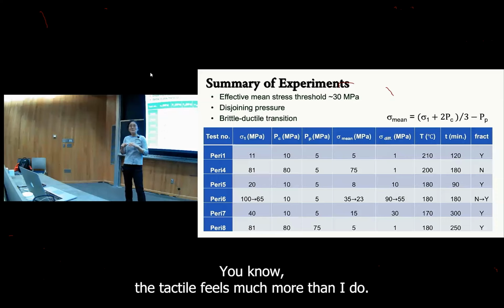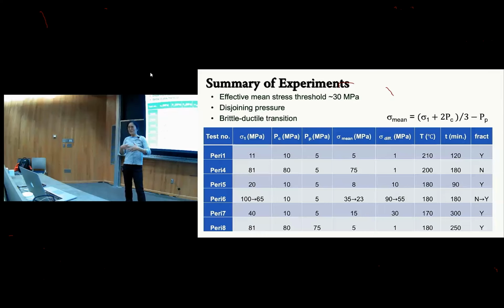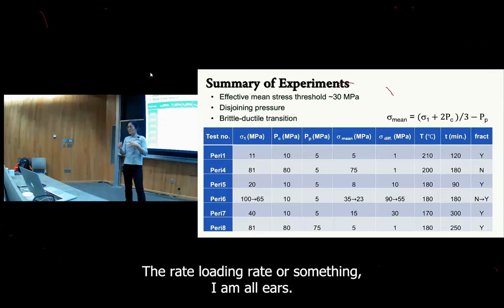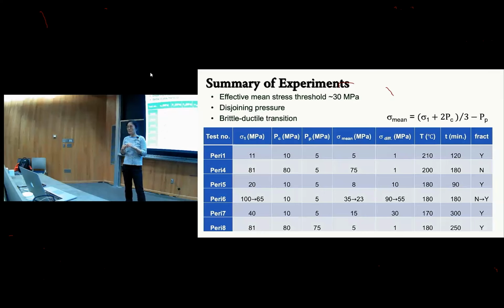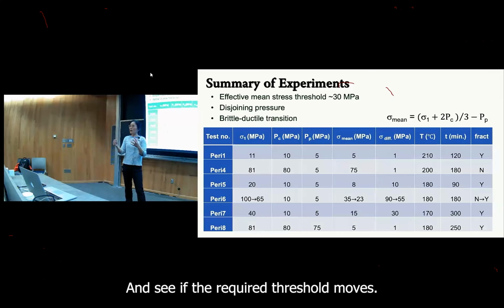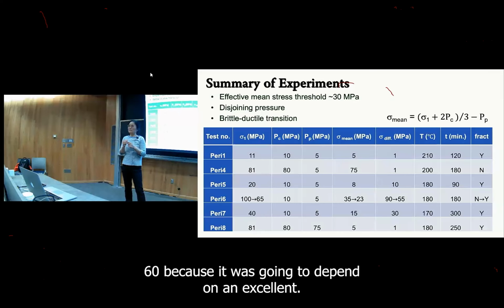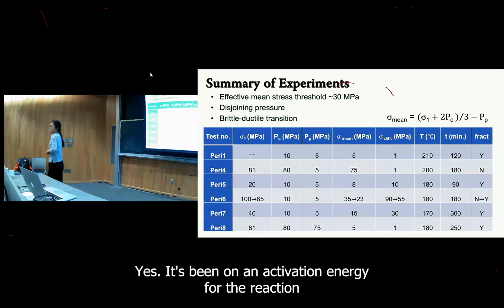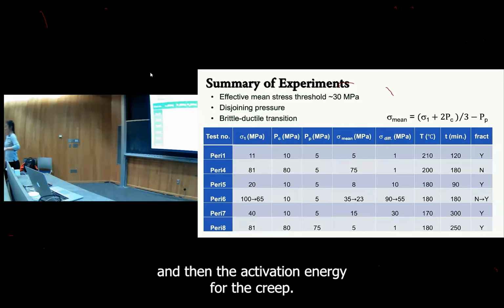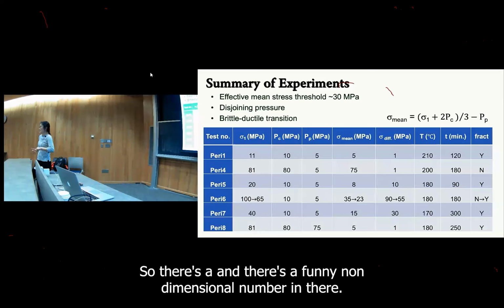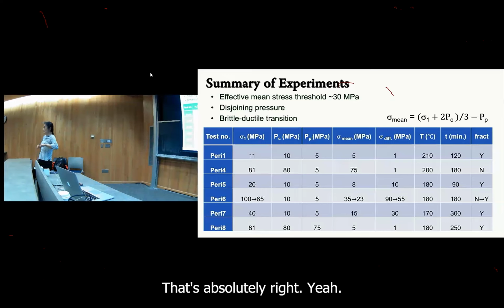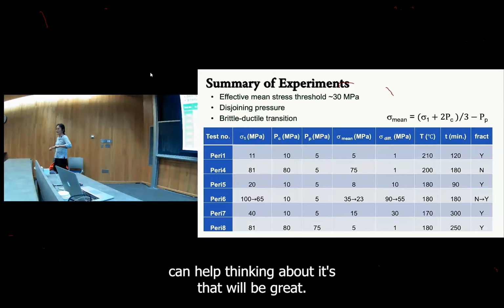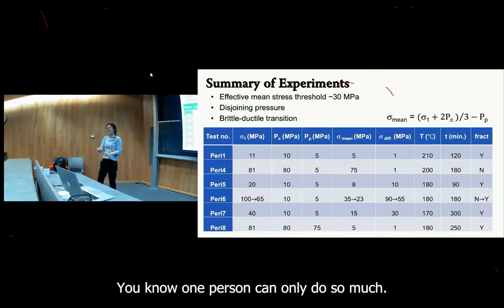You know the ductile fields much more than I do, but if you have ways to change the loading rate or something, I am all ears. But yes, in September, the first 3 experiments we want to do would be to drop it to 150 and see if the required threshold moves, especially because it's going to depend on an activation energy for the reaction and then the activation energy for the creep. Yeah, there's a funny non-dimensional number in there. That's absolutely right. But if you can help thinking about it, that will be great. One person can only do so much.